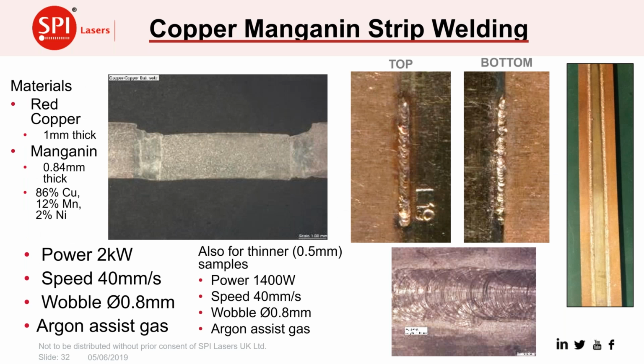And just starting to look at some dissimilar metals. This was a copper and a manganin. This was done for a particular application, but you can see the red copper strips on the outside and the manganin in the middle, where we've just done joints down each side to join it together. The welds, top and bottom, you can see they're looking neat. There's a little bit of undercut at the top, but we're using no filler on this. To keep the surface bright, we've used an argon assist gas in this situation. So butt welding as well as bead on plate and lap welding are well able to be done with these oscillation welding situations.